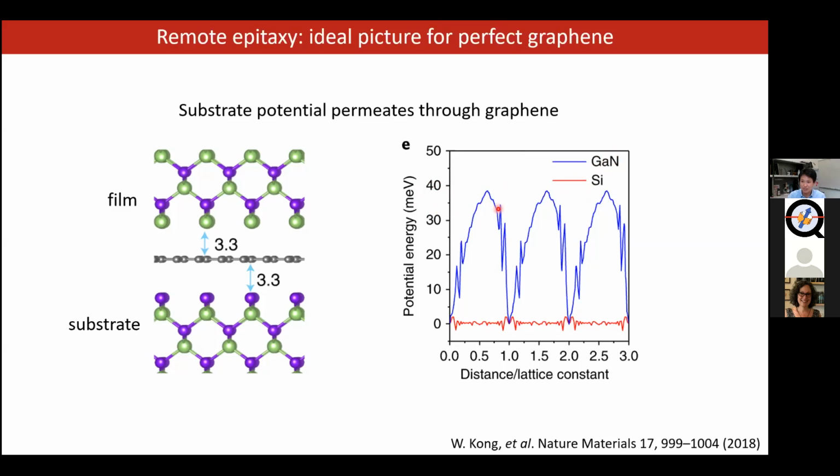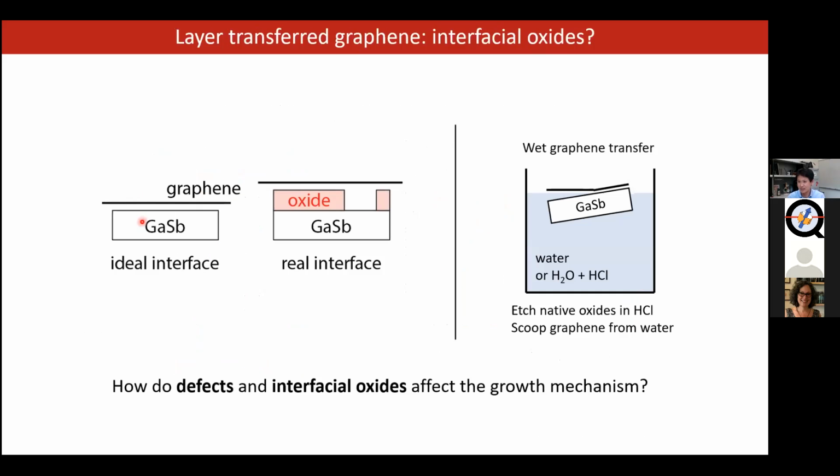And if you compare that to typical values of kT at a growth temperature, let's say around 500 or 600 degrees C, now you're talking about kT values of order about 100. Okay, so these are values that are small compared to the thermal energy. So is this really enough to seed epitaxy? And then if you ask the question, well, if there are also defects, which are probably even larger fluctuations than this, would the defects dominate the growth mechanism? And the reason why we're particularly keyed into these defects is the fact that we don't expect the graphene substrate to be as clean and long-range defect-free as the ideal case would lead you to believe.